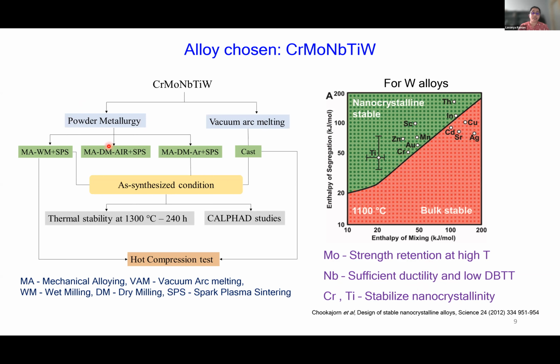In that, we try to synthesize the alloy using wet milling conditions. When I say wet milling, we use a process control agent, toluene, so that the powders are immersed in it when we make the alloy. And in dry milling, we don't use any PCA. In the dry milling, we varied the atmosphere in which we make these powders. One was done in air, and another was done in an inert argon atmosphere.